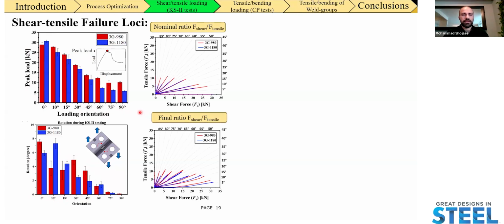Now, what we can do from this data is that we can decompose the peak load into its constituents, which are shear load and tensile load nominally, which is done at the top here. So that means, for example, if a test is performed at 15 degrees loading orientation, we're going to assume that the weld is going to maintain its alignment from the very beginning to the end of the test. But if we actually account for the actual orientation of the weld from the beginning to the end, we can see that the evolution does not follow a linear trend, and it actually curves upwards, where we get more contribution from the tensile component of force being applied to the spot welds.